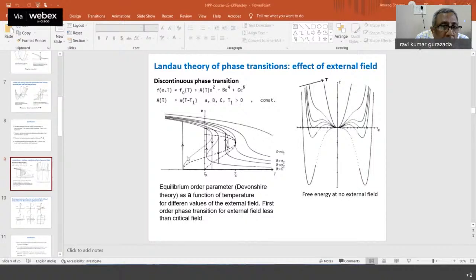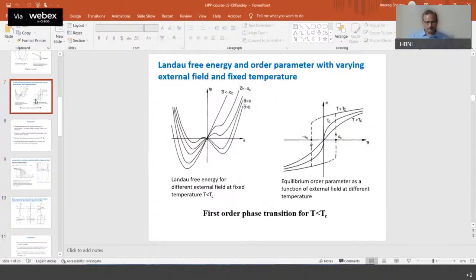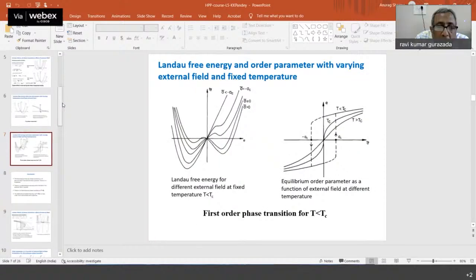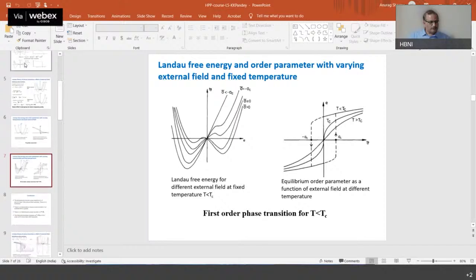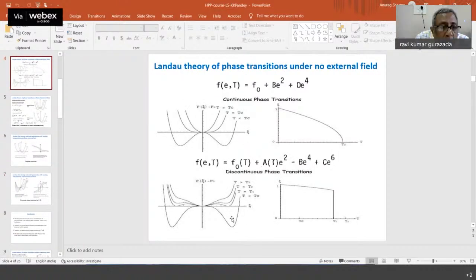Yeah, so I am basically considering two extreme temperatures, the spinodal temperatures, T1 and T2, as I have shown in this curve. If you don't have any field, you can define two temperatures, T1 and T2. When your daughter phase just starts becoming stable, you have an inflection point here. It is still not a stable phase, but it starts becoming stable. The phase transition does not happen here. Phase transition would happen when the energy of this phase is lower than this, and of course at temperatures where thermal fluctuation can allow crossover of this barrier.